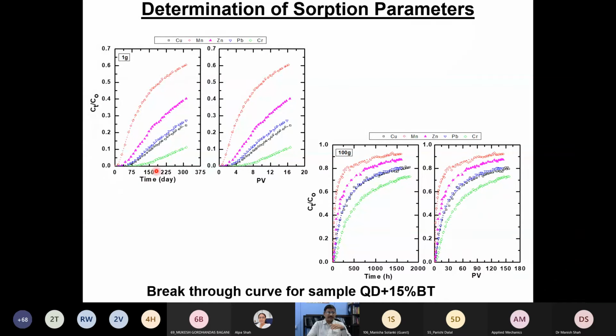So in view of this, we know the seepage velocity, and we know the time at which we collected the sample, so we converted the same data in terms of the pore volume. What is the meaning of pore volume? Pore volume is basically the porosity of the system, the void volume of the sample, and you know how much quantity of water is being collected. If you normalize the collected water by the pore volume of the void, then this becomes the pore volume. This is very much needed when you want to compare the breakthrough curves obtained from the 1G environment versus the 100G environment in the geotechnical centrifuge, and then we got the same kind of response.